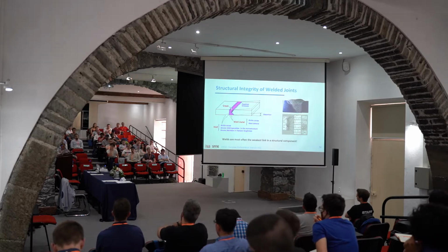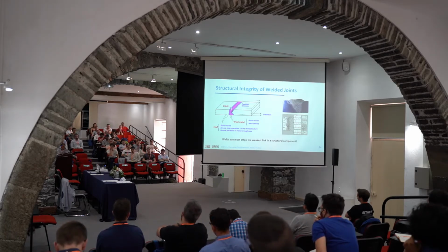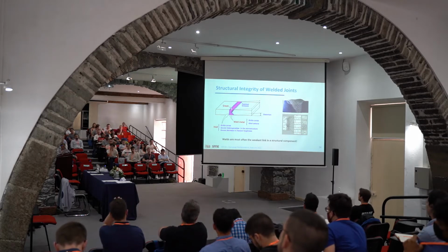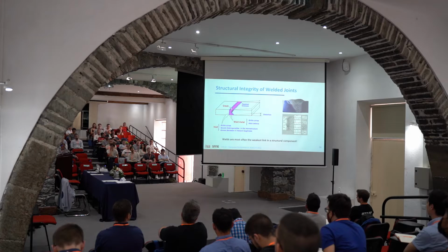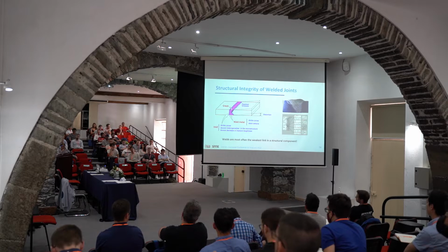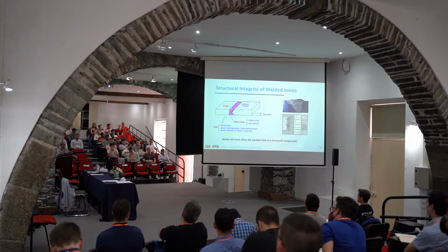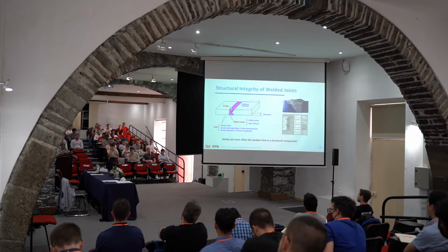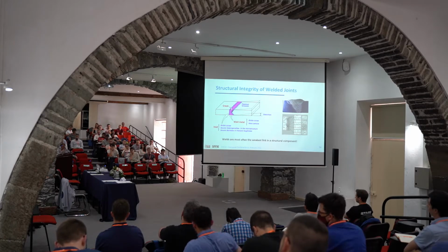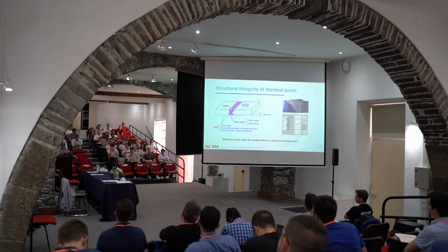So usually you stay very close within a very narrow band in temperature. So you have a very fine microstructure. Then you roll the plate, so the microstructure is elongated. So you have very nice properties, mechanical properties and toughness, especially fracture toughness. And then you send this to the shipyard. You send this to the pipe shop, to the plant, and the materials need to be put together. Okay, so it's different than composites. The process is different, and the process of putting the metallic structures together is by welding.